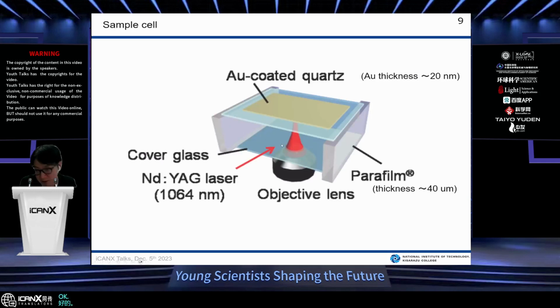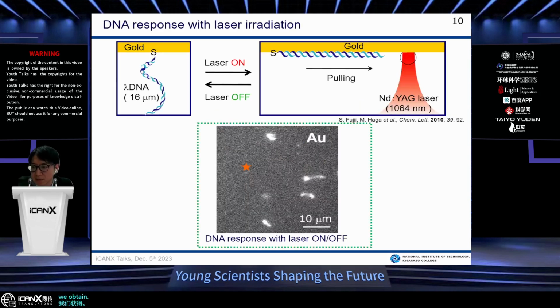Okay, let's move on to the first result we obtained. The first experiment was performed using DNA molecules, with one end immobilized on the gold surface by gold-thiol interaction and stained with fluorescent dye. So this is a fluorescent microscope image of DNA. Usually DNA is shrinking, so this shape. Let me show the movie of the response with laser irradiation.